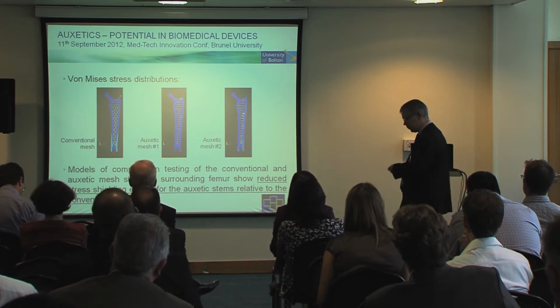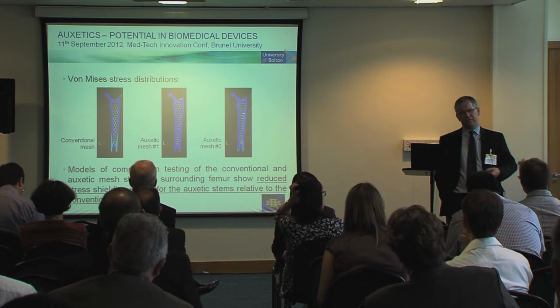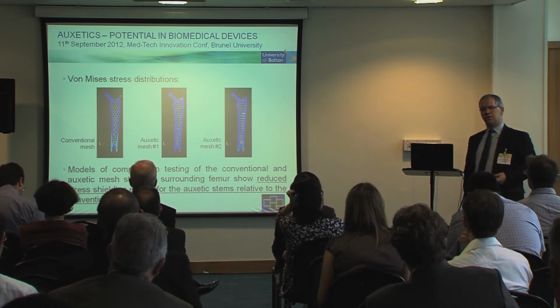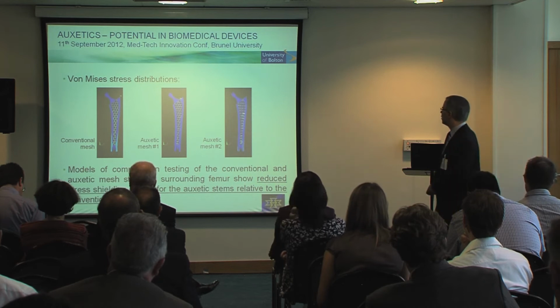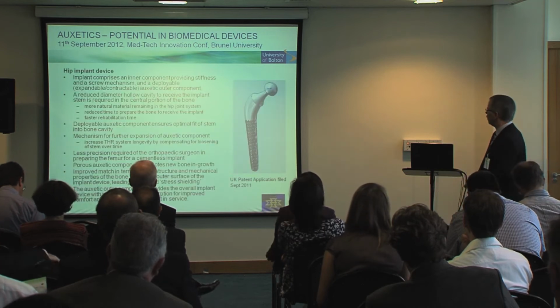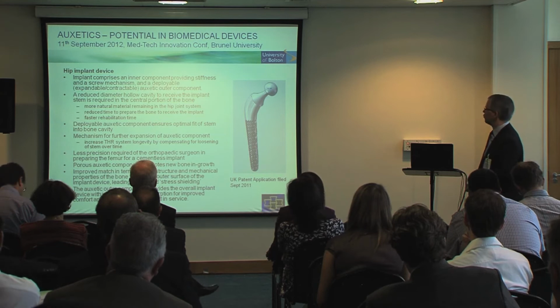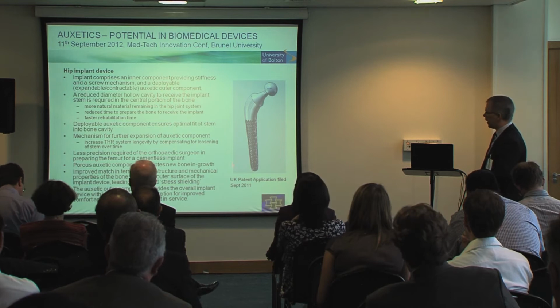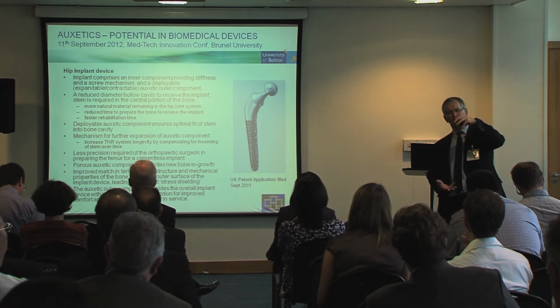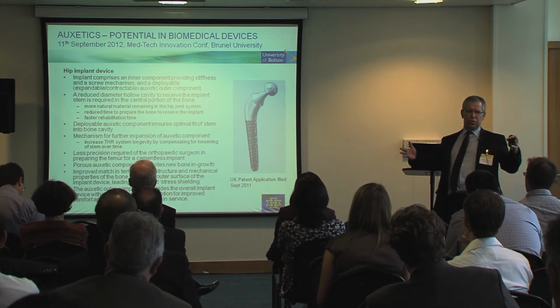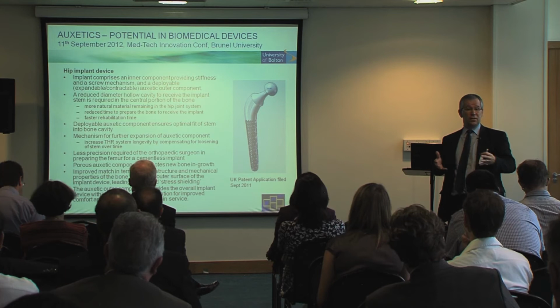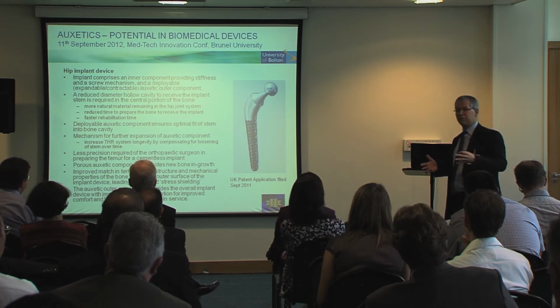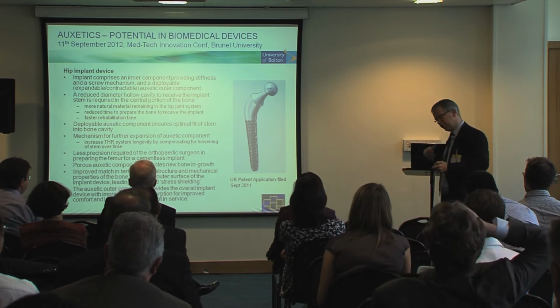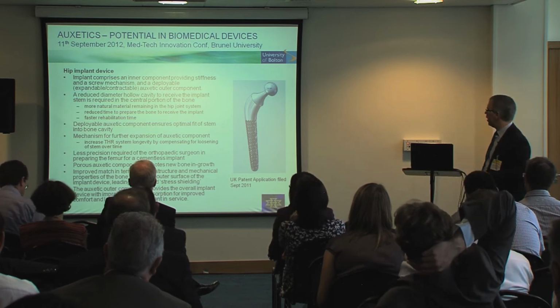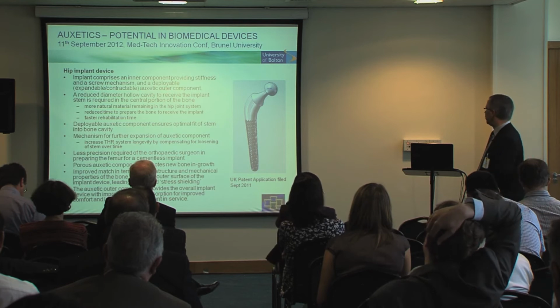So we believe that by careful design of the mesh geometry to give you the auxetic effect, we can reduce the detrimental stress shielding in hip implant devices. And in fact, that's one of a number of potential applications or benefits we can see for these devices. We could also put in there an inner screw mechanism to give us a deployability function. I'm not talking large strain deployability here, but enough to tighten a device once it starts to loosen in some way without having to completely replace the device. So we'd have to think about it a bit, obviously, about the engineering that would require, but our initial studies show that should be feasible.